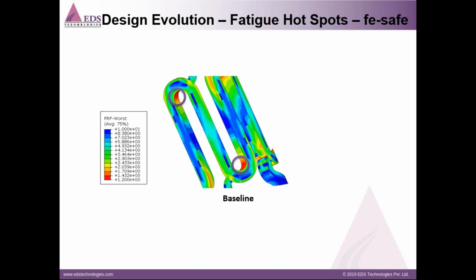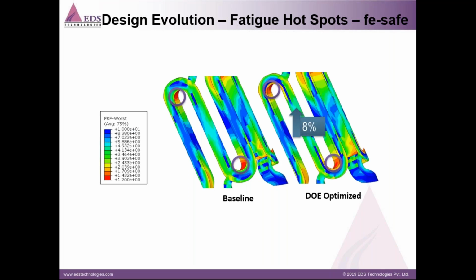The second factor that we want to look at is the fatigue hotspot. The same region where the stress was higher will also lead to the lowest fatigue factor, and those are the two regions for which the fatigue factors are the lowest. After the DOE study, you can see that the optimized stent leads to an 8% improvement in the worst fatigue factor. That means the fatigue factor has improved by around 8% in these two highlighted regions. Let's say initially it was 1.2, and it has improved slightly to a larger value.